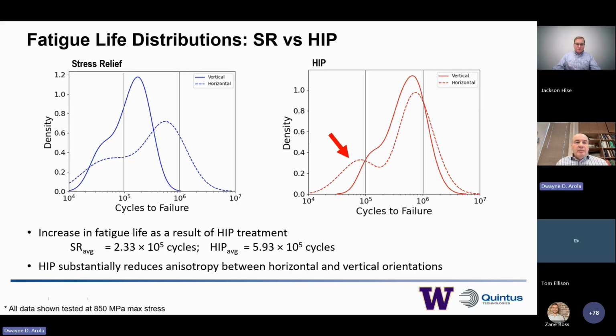So here I'm comparing fatigue life distributions that are developed from the stress relief treatment and the HIP treatment. This is, of course, presented here, as you see, for both the vertical and the horizontal orientations. This is a result of metal from 3 different partners. These are presented as kernel density estimate distributions. These are just like histograms, and the only difference is that it's presented here as a continuous curve rather than individual bar distributions. This makes it easier to compare small nuances of the distributions.